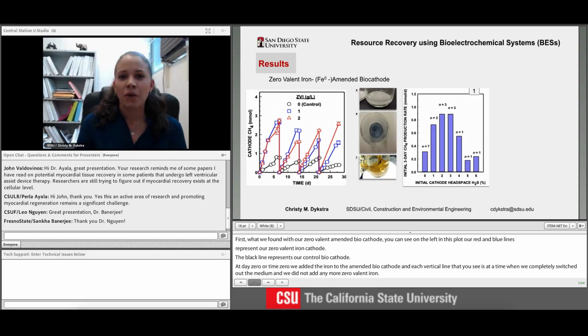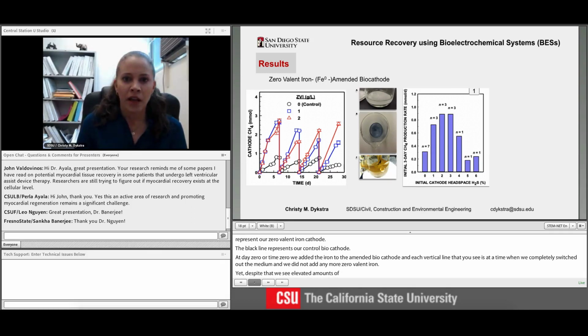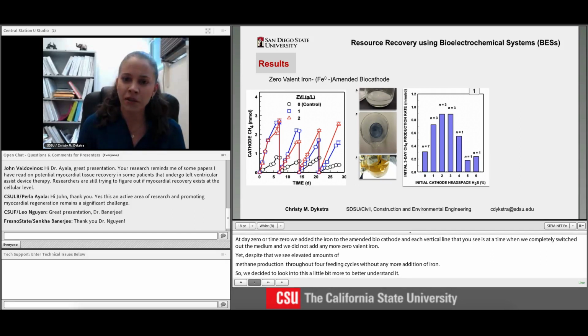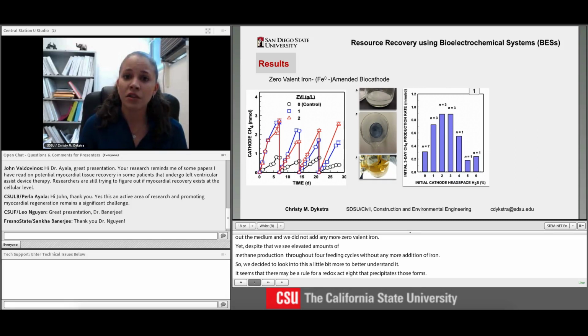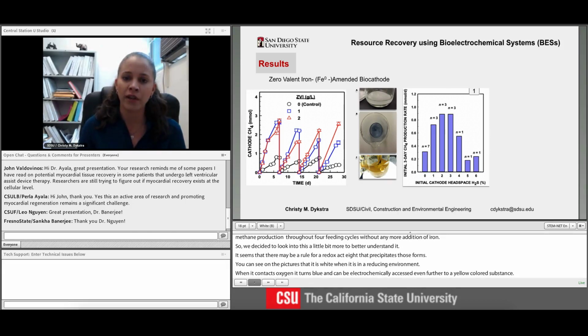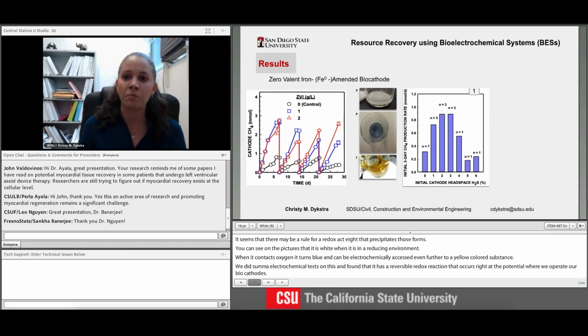So we decided to look into this a little bit more to better understand it, and it seems that there may be a role for a redox active precipitate that forms and coats the biocathode. You can see on the pictures that it is white when it's in a reducing environment. When it contacts oxygen, it turns blue, and it can be electrochemically oxidized even further to a yellow-colored substance. We did some electrochemical tests on this and found that it has a reversible redox reaction that occurs right at the potential where we operate our biocathode. And so we hypothesized that this is playing a role in improving our electron transport and improving cathode methane production, even without the addition of more zero-valent iron.